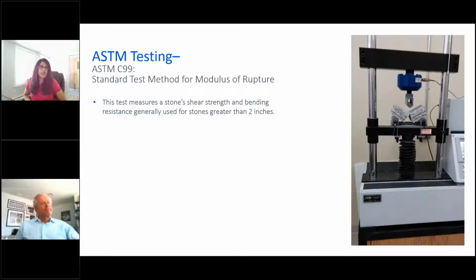So the next one is the ASTM C99, the standard test method for modulus of rupture. This test measures stone shear strength and bending resistance, generally used for stone greater than 2 inches. This test method and the flexural test method are interchangeable depending on the application. We may need either, or sometimes both are required.